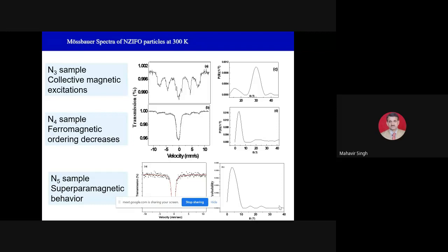There is clear relaxation. The top one is simple collective magnetic excitation, but as we reduce the size, there is a shift, which is a clear transition from bulk magnetic excitation to superparamagnetic transition. There is clear indication from Mössbauer spectroscopy, and simultaneously we have fitted it with a distribution function. It clearly matches with the XRD. Dear students, if new students and research scholars are there, you can correlate magnetic results with XRD. If you want to correlate XRD of bulk and XRD of nano, in nano the XRD pattern is broad, but in bulk the XRD pattern is sharp.